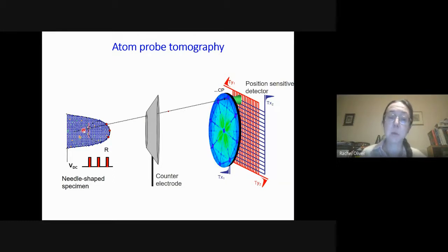Now, that will give us an XY position for these atoms. And we also have information about their Z position simply by their arrival time, because we can't have atoms from back here in the needle evaporating before atoms at the apex of the needle here. So that gives us the X, Y, and Z coordinate of each atom. And we can also work out what atoms they are, or what ions they are as they evaporate. And that's because a heavier ion will take longer to fly from the needle to the detector. So if we measure that time of flight, we can use it to do mass spectrometry and to find out what atoms we have present, all of which gives us X, Y, Z positions and atomic identities. It allows us to build up compositional maps in 3 dimensions.